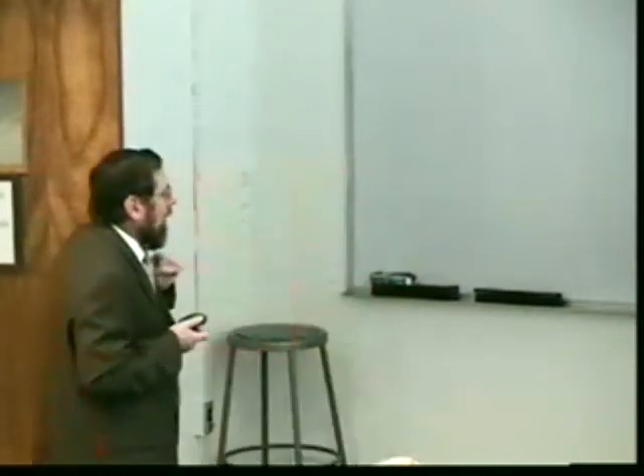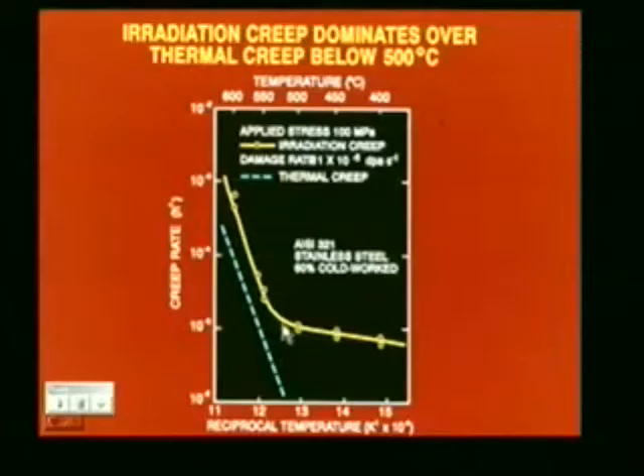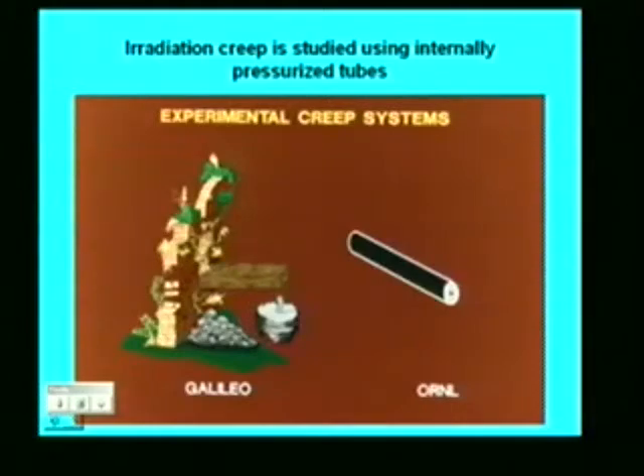But if it's in an irradiation field, we see that even at the low temperatures, we have a significant creep rate that remains. And it has a very weak temperature dependence, maybe even none at all. That's quite an interesting phenomenon. Well, how do we study it? Well, Galileo had all the right ideas. He was a clever fellow.